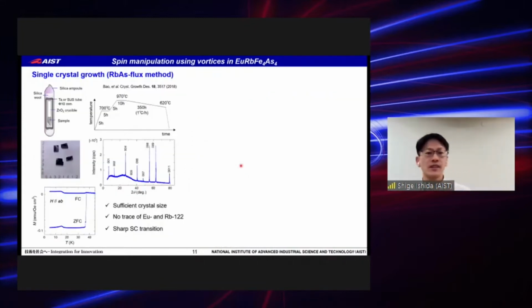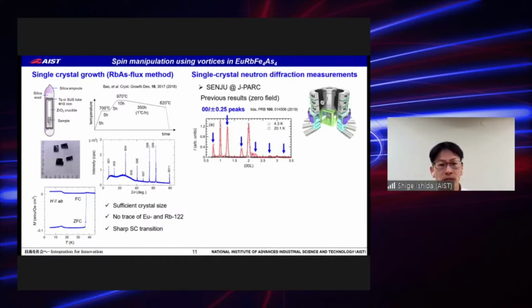Motivated by this idea, we grew single crystals of Eu-Rb-1144 using the rubidium arsenide flux method, following the Bao's work, and obtained millimeter-sized single crystals. Magnetization shows a sharp superconducting transition and a kink feature corresponding to the magnetic ordering of europium moments. XRD pattern shows no trace of 1-2-2 phases, and using these high-quality single crystals, we performed neutron diffraction measurements.